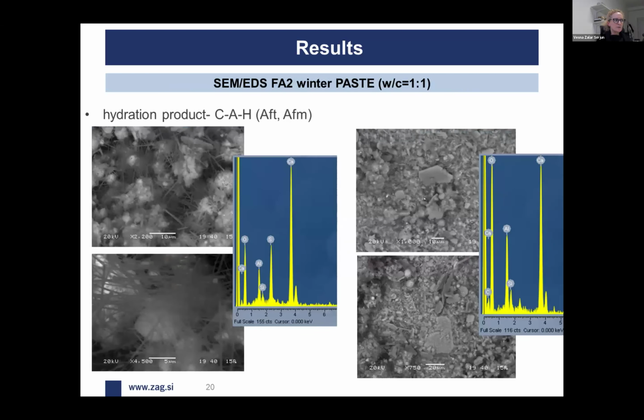Those hydration products can also be nicely seen on the surface of those pastes. Electron microscopy showed the presence of needle-like ettringite type hydration products. Also, EDS confirmed the appearance of this ettringite phase. And on the other hand, we also confirmed the presence of calcium aluminates, like the platy ones I was talking about, representing the hemicarboaluminates and monocarboaluminates.